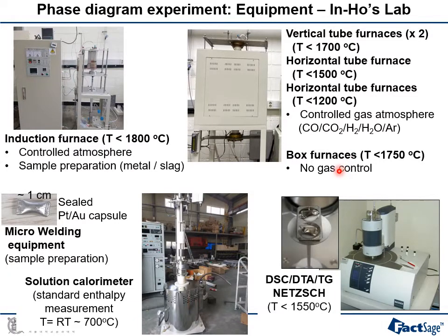In our lab, we have many high temperature furnaces designed for phase diagram study. And we also use thermal analysis equipment. Recently, we developed our own solution calorimeter, which can be helpful to measure the standard enthalpy for the compounds and the solution phases. And in many cases, we also use the so-called sealed platinum capsule technique for the phase diagram study.